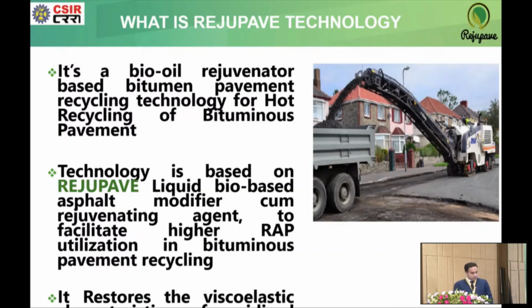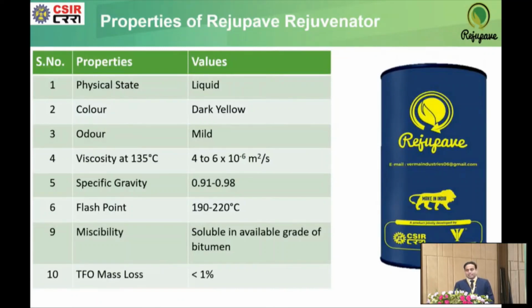mixes. This rejuvenator is a kind of bio-oil based liquid rejuvenator which we can utilize directly in the bitumen tank along with the virgin bitumen binder, or can spread directly in the pug mill on top of the reclaimed asphalt pavement material. With the help of it, you can recycle the bituminous mixes of dense bituminous macadam, bituminous concrete, semi-dense bituminous concrete, like that. Besides that, you can also use it in stone matrix asphalt.